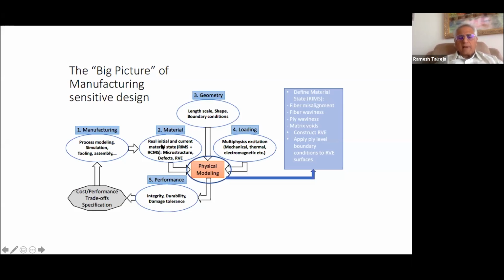What I'm doing, and similar work in the literature in failure analysis, is to take that manufactured composite and characterize its internal material state, and I have called that RIMS, which is real initial material state. And as loading progresses, the initial goes to current, so the material state evolves. And that evolution depends on the defect structure in the microstructure. So there's a stationary part of the RIMS that does not evolve, obviously, such as fibers and matrix, but defects become cracks and they evolve and they affect the performance.